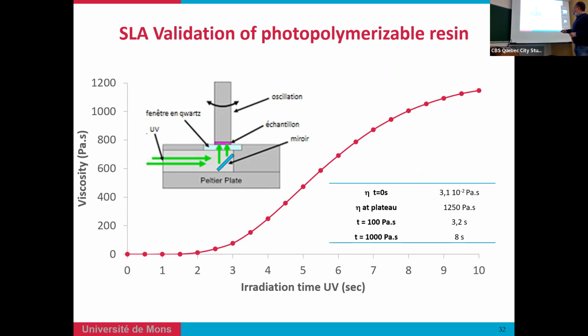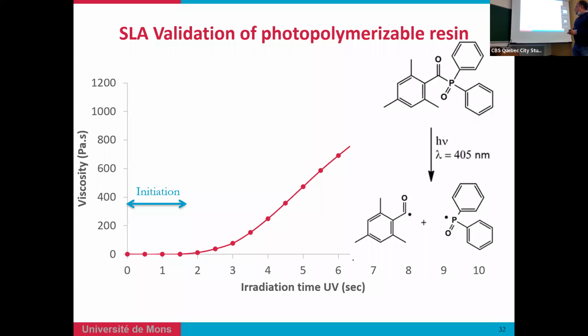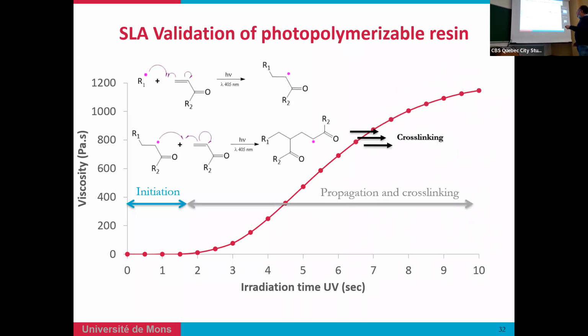You have to follow the viscosity against the irradiation time. When you apply a certain light, you have the first stage involving initiation, meaning the release or decomposition of the radical that can attack the monomer through different pathways. At the end you have propagation and crosslinking, so the system builds up and you get an increase of viscosity.